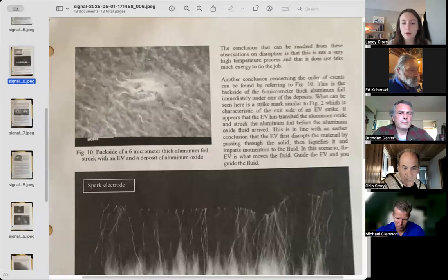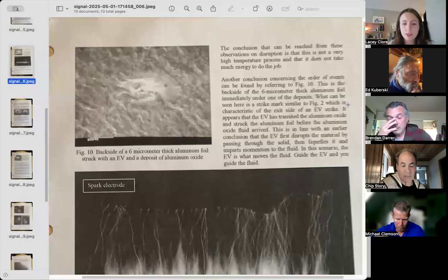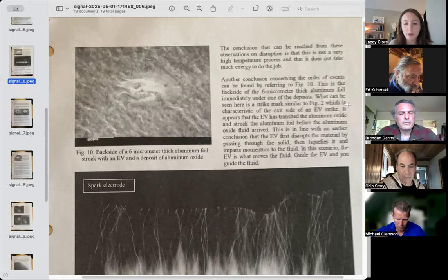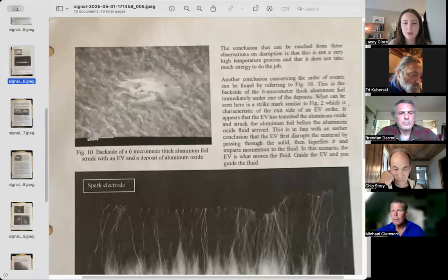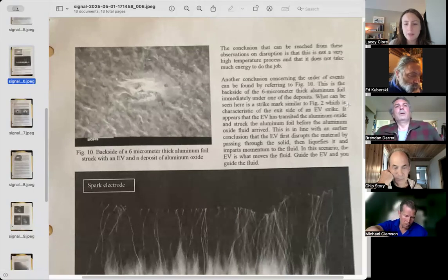Another conclusion concerning the order of events can be found by referring to Figure 10. This is the backside of the 6 micrometer thick aluminum foil immediately under one of the deposits. What can be seen here is a strike mark similar to Figure 2, which is characteristic of the exit side of an EV strike. It appears that the EV has transited the aluminum oxide and struck the aluminum foil before the aluminum oxide fluid arrived. This is in line with an earlier conclusion that the EV first disrupts the material by passing through the solid, then liquefies it and imparts momentum to the fluid. In this scenario, the EV is what moves the fluid. Guide the EV and you guide the fluid.